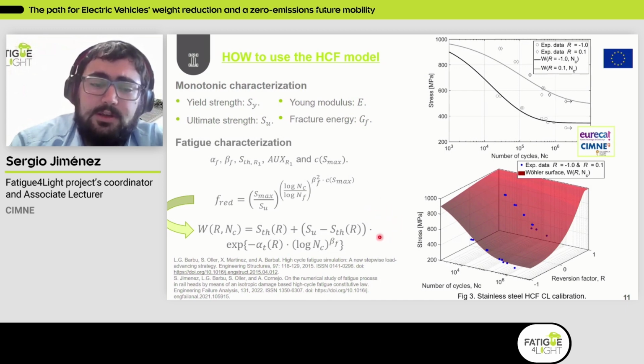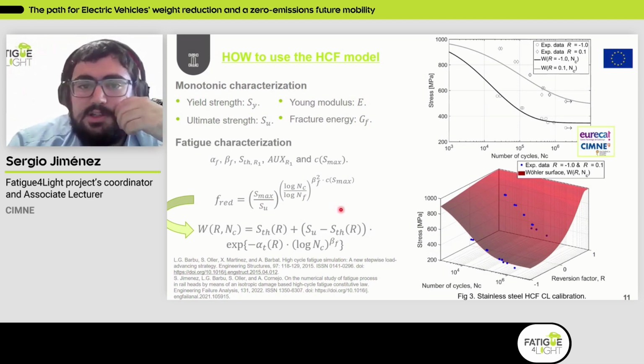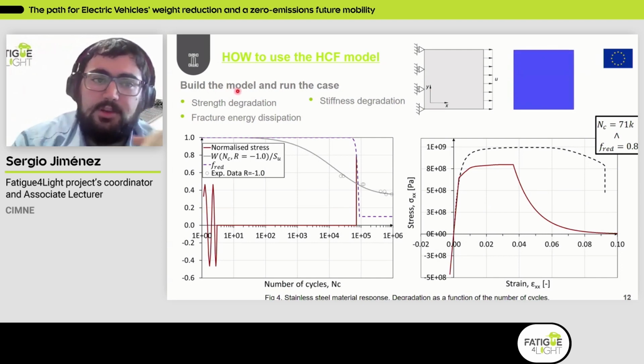the approach that we follow is that, together with this mathematical definition of the degradation in the material due to cyclic loads, we also have defined this mathematical representation of the Wöhler surface. So basically, we are using exactly the same parameters in both expressions, and we connect both expressions in such a way that by calibrating this Wöhler surface, we are indeed calibrating the fatigue response in terms of the fatigue reduction function. So by doing this, which is quite an automatic process, we end up with the complete characterized model. And then it's time to build your model, the geometry, and run the case.